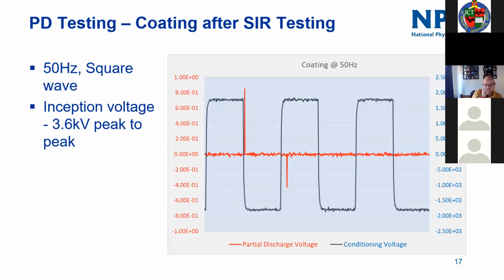If you start to put a square waveform, in this case, across it, this is just at 50 hertz, you can see partial discharge occurring periodically through the system. And that's got an inception voltage with this square waveform of about 3.6 kilovolts peak to peak.